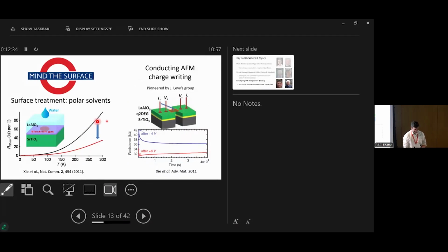Since we're in London, I stole that logo. The problem with these materials is that they're very sensitive to just about everything, and particularly this very thin layer of oxide on the surface. So you have a few nanometers of some material, and then this conducting interface underneath it. So actually, if you do anything to the surface, you're probably also going to interact with the interface below. So we found actually that cleaning the system with water or acetone or ethanol, any polar solvent, actually field effect gated the system. So that's kind of tricky for an experimentalist who likes to keep their samples clean.